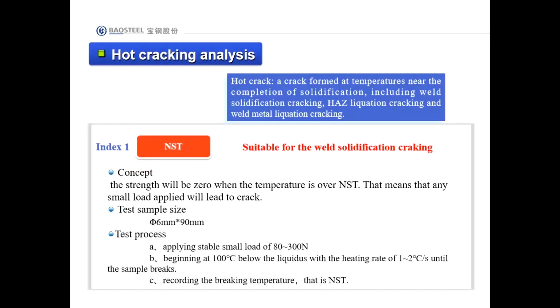The NST can be used as a criterion for weld solidification cracking. What is the NST? That means the strength will be zero when the temperature is over the NST. That means any small load applied will lead to a crack.